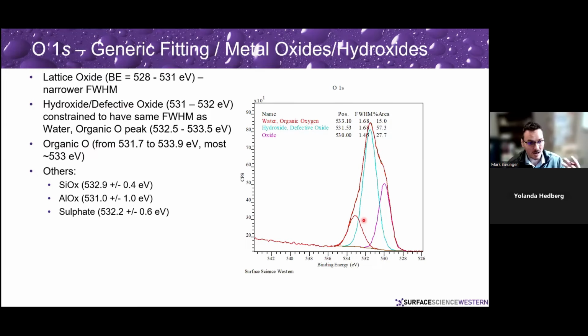And you can do that for other things, aluminum, for example. Sulfate's another one. You see a little tiny sulfur peak, but you multiply that by 4 if it's sulfate. It's a lot of oxygen that shows up in that oxygen peak. So those are the sorts of things you can think about as you're looking at that oxygen peak.